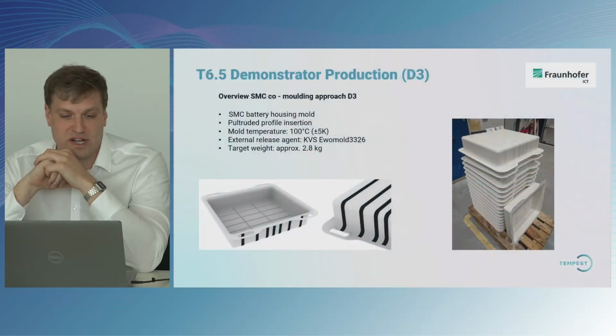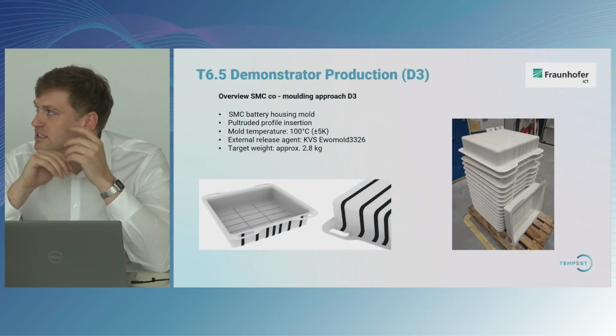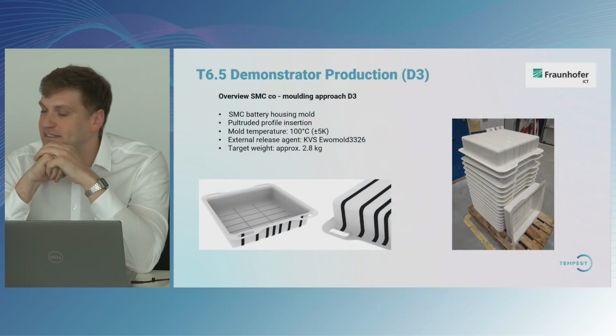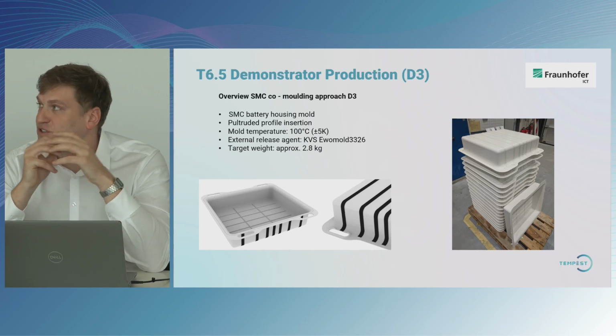However, with regard to the manufacturing, here we came up with an innovative approach, a co-molding process, which is that with this demonstrator 3 we had the highest energy storage, thus resulting in the highest battery cell weight, and therefore we needed a really structural, integrative, and stiff solution.